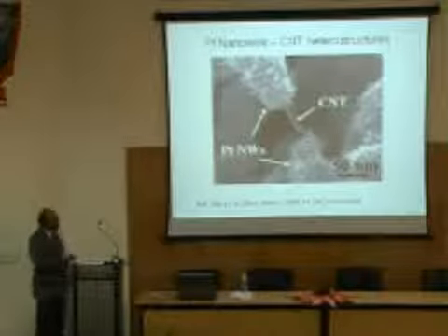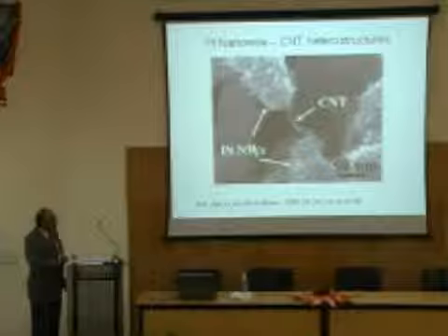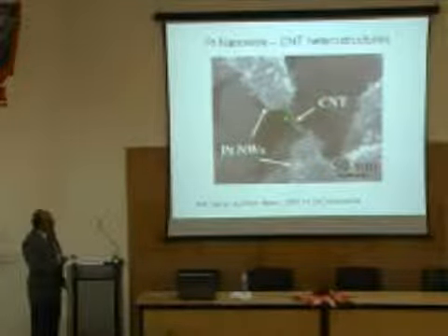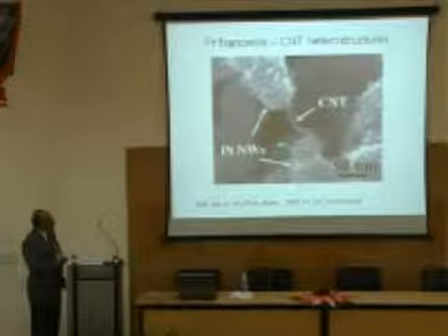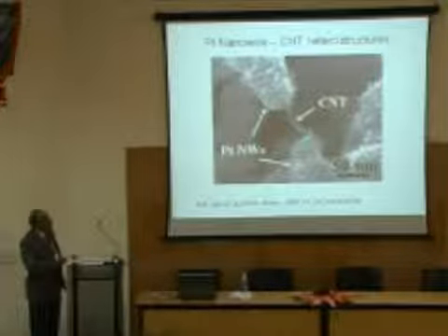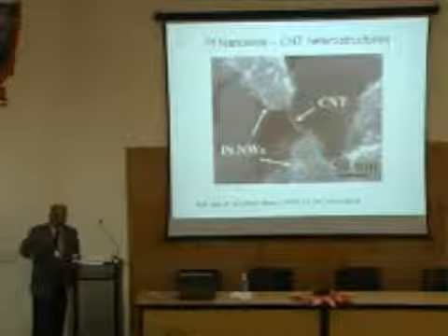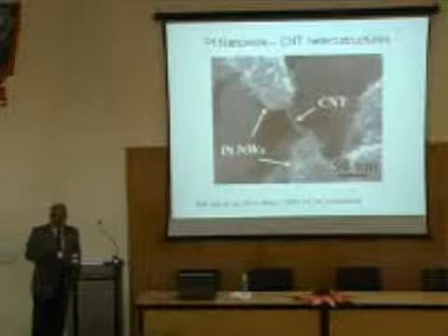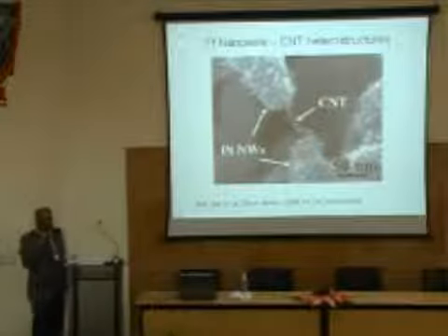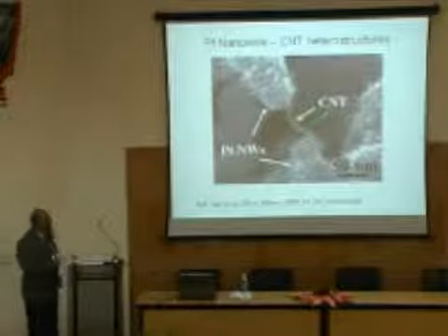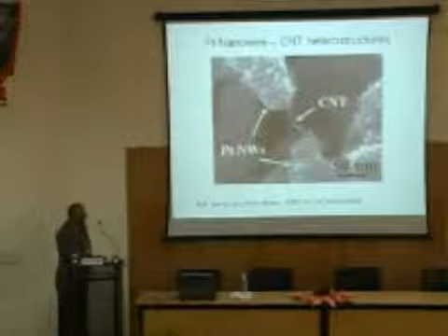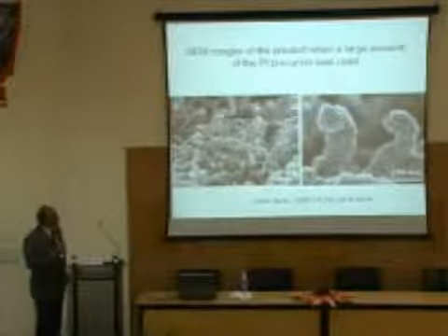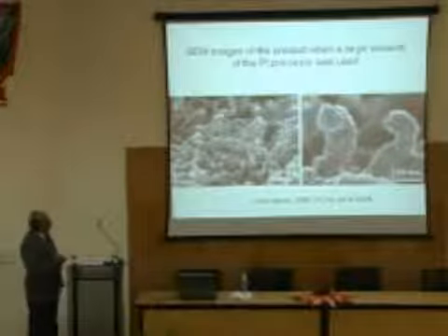This is the SEM or TEM picture of that carbon nanotube, and you can see the platinum nanowires growing on top. Because platinum will be much more conducting, you have a junction, because for the carbon nanotube you can choose a semiconducting carbon nanotube. So you can use it in devices as junctions, as a metal insulator junction or metal semiconductor junction. These are more high resolution pictures.